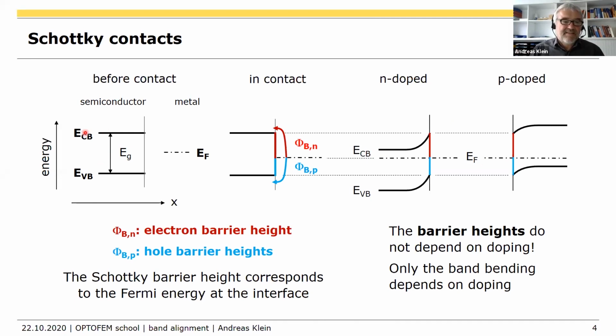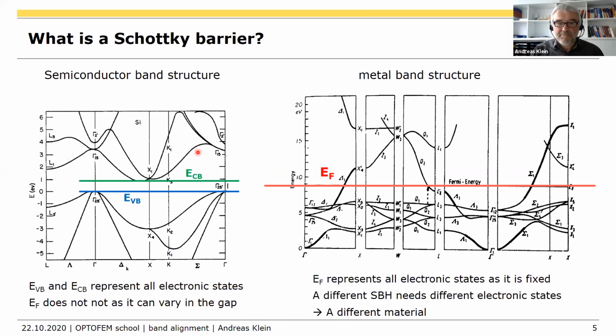Okay, what does that mean, these lines, the conduction band and the valence band and the Fermi level? What is that? In principle, it is a representation of all electronic states of the material. So that's the band structure of a semiconductor. You see here, this is for silicon, from a book. The valence band maximum is here and the conduction band minimum is here. So if you want to move these levels, the conduction band and the valence band, in principle, you have to move all electronic states. But the Fermi level can very easily vary in the band gap, because very small concentrations of dopants can shift the Fermi level quite a lot.